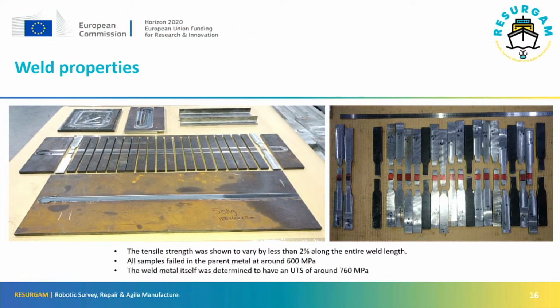This shows some of the work we've been doing. So we've been taking some big, large plates of steel, making a friction stir weld down the middle of them, and then cutting those up into test pieces, and they're being tested for strength, toughness, elongation, hardness. Some are now being tested for fatigue as well. And what we're trying to demonstrate is that the properties are consistent along the weld from beginning to end, and also determining what those properties are.